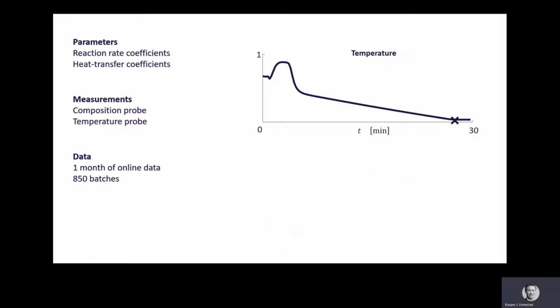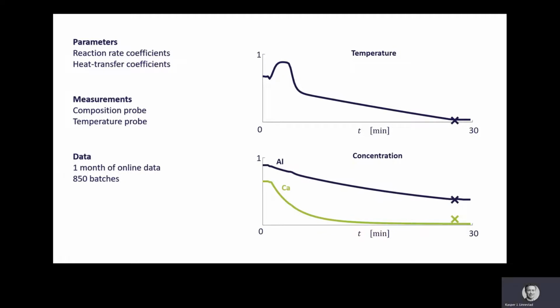With a temperature profile for a single batch, we can see that the temperature rises early due to exothermic slag forming reactions and falling rapidly due to addition of alloying elements and cooling material, before finally falling slowly due to heat loss. Presently, only the initial and end temperature is available, but hopefully we will be able to get more measurements during the refining from the infrared cameras and the machine vision algorithms.